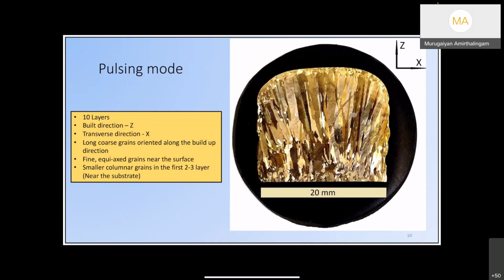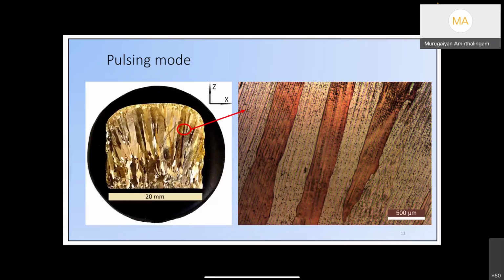So the microstructure would be like what is over here, and that is a problem, isn't it? We cannot use this microstructure in real life, and when you pull it in tensile mode or apply a fatigue load, this is going to crack. It is going to fail prematurely compared to, say, a forged or rolled or annealed component. And you can also see the microstructure development. So this is one pass layer. When we solidify, we also slightly melt the previous layer, and the grains grow with the steeper temperature gradient in a planar mode by inheriting the parent microstructure orientation. In metallurgy, we call it the cube edge direction, which is the 100 direction. No need to worry about it. What you see over here, it inherits the orientation and grows along this direction.